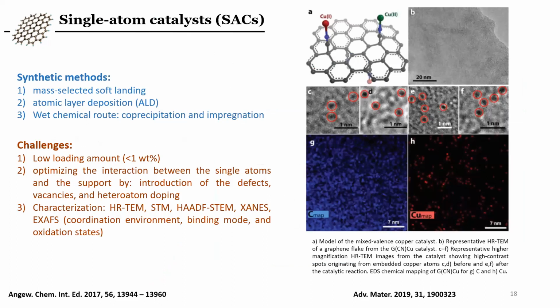There are different ways to prepare SACs. The feasible one is the wet chemical route, which we use. But there are challenges here. You need to have low loading amount, because if you increase the amount, aggregations will start and nanoparticles will be obtained, which we don't want. We need to optimize the interaction between the single atom and the support by introducing defects, vacancies, and doping. And also high-end characterization methods are required.